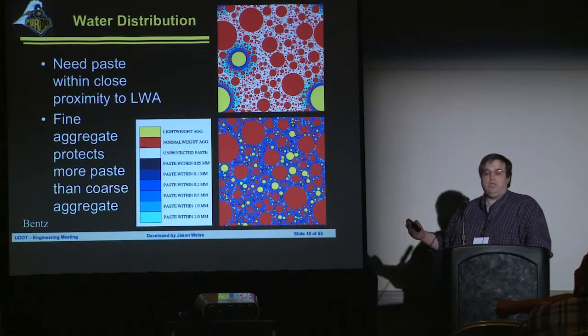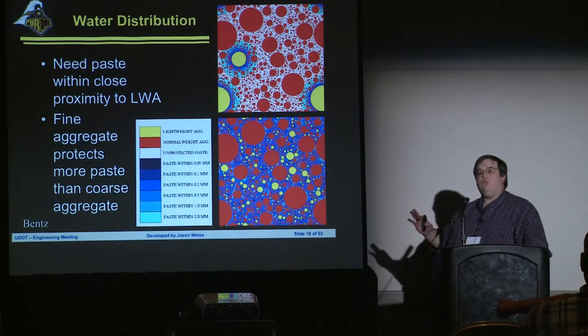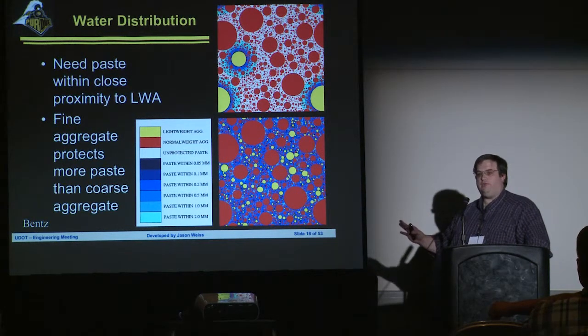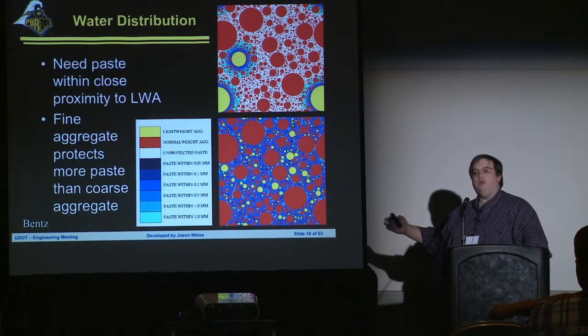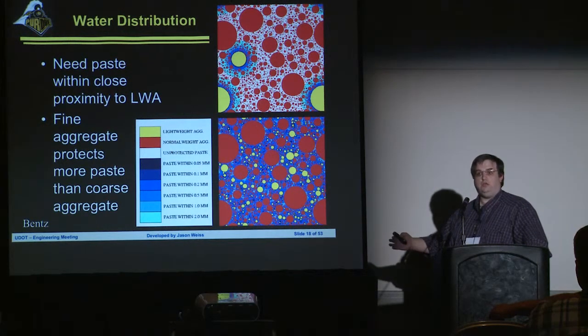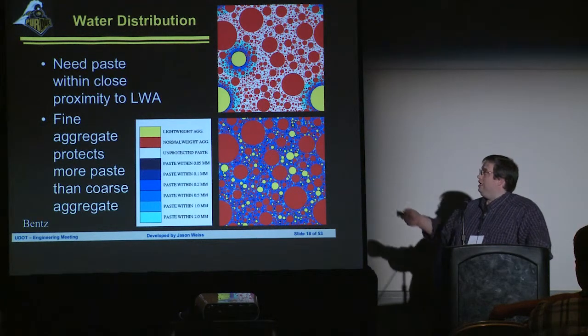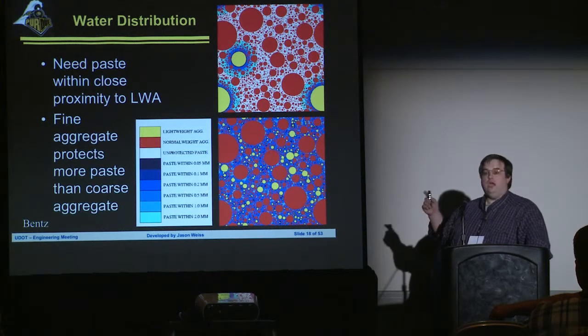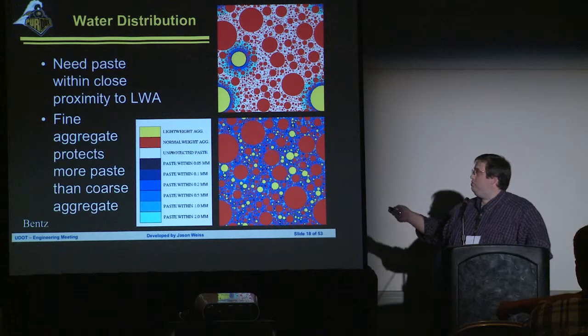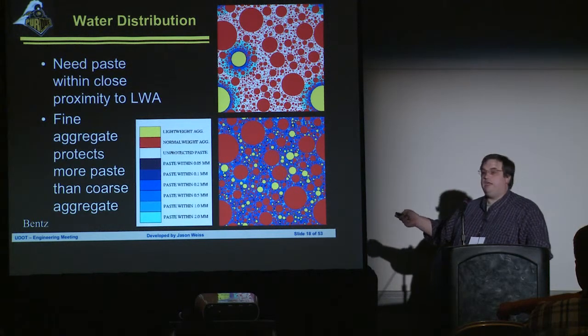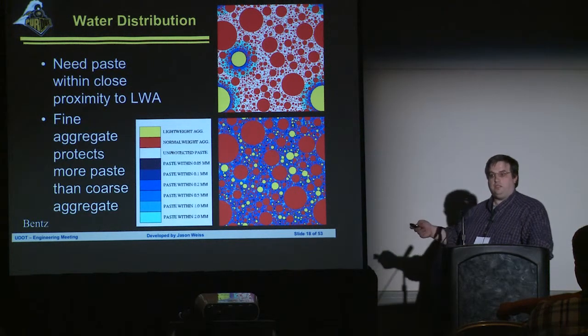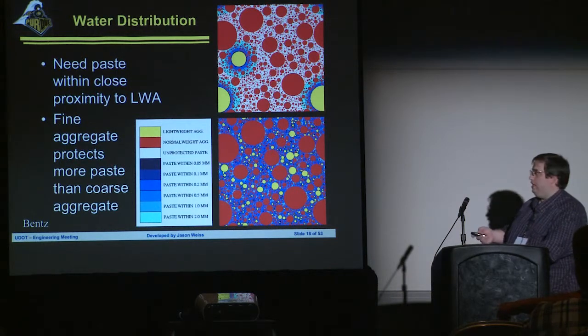I'm not going to go into it here, but we've done a lot of work with a technique called neutron tomography. It's like a CAT scan that instead of using X-rays uses neutrons. We can essentially find out that the water only moves about 3 to 4 millimeters in some of these high-performance concretes. So the real goal is to not necessarily use a particular volume of aggregate, but to make sure that we're using a volume of aggregate that's well distributed throughout the system, replacing a portion of the sand.